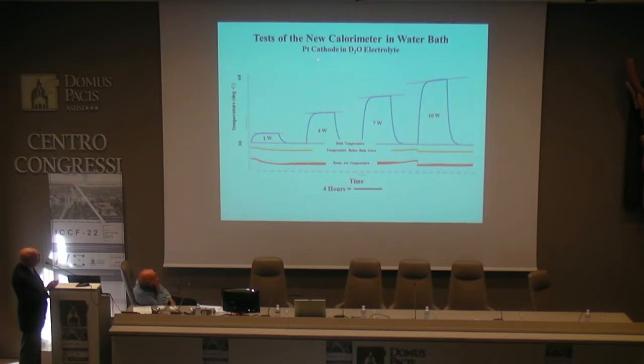This is a plot of some of the calibration data, time here, temperature here. This was a platinum cathode in a deuterium electrolyte as close as possible. So when we would put in 1 watt of electrolysis power and then turn it off, 4 watts, turn it off, 7 watts, and so forth. And this is the bath temperature here. This is the temperature in the air above the water underneath the plastic cover, and this is the room temperature. We still have a problem with room temperature control, but we're about to fix that.